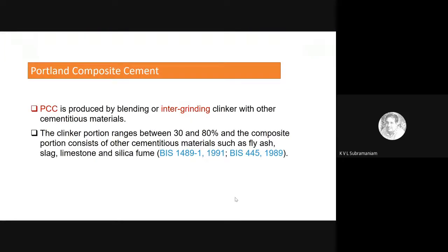So, but what about Portland composite cement? Now, Portland composite cement is produced by intergrinding or blending clinker with other cementitious materials. Now, where it is different than pozzolanic cements is that we intergrind this. We intergrind slag or clinker with this, and we use multiple sources of silica or multiple materials in this intergrinding process. And the composition or the replacement of clinker can go from 30 to 80%. And basically, we can use different supplementary cementitious materials like fly ash, slag, limestone, and silica fume, and combinations of these. So we're not restricted to using only one material. And now there's even a BIS standard available for composite cements.